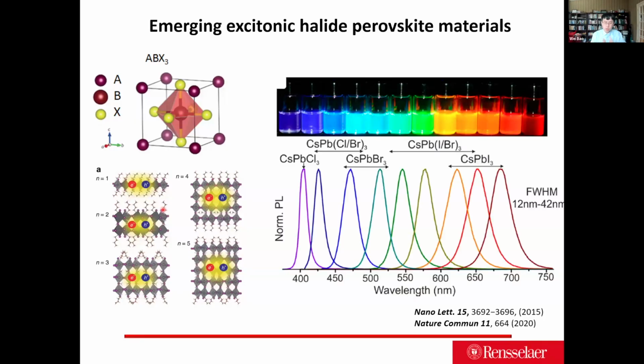And because the material is really highly tolerant to defects, for example, take the inorganic cesium lead chloride, bromide, iodide group as a halide perovskite, you shine UV light on them, and with nanoparticle synthesis in the beaker, you can really see the photoluminescence with the bare eye. Such a property, combined with the sizable exciton binding energy, made me really excited about it. Plus, the photoluminescence is really tunable. The quantum yield is really high. Some of the materials, even solution processed, reach as high as 50-60%, almost comparable with the best gallium arsenide you grow over the MBE chamber.